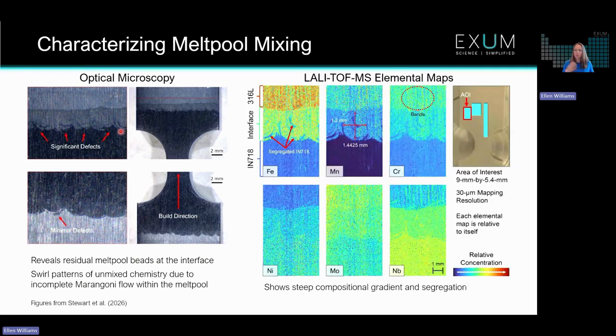And there's a process of Marangoni flow that creates these swirls that you see, especially in the upper interface here, where we see these defects or areas with swirl patterns where the material was not completely mixed after the material was switched. So we're able to see this with optical microscopy. But then what LALI-TOF-MS allows us to do is actually determine the chemistry of this interface as well as these swirls. So what you're looking at here, LALI-TOF-MS analyzed an area essentially over that top part of the stainless steel to nickel interface.